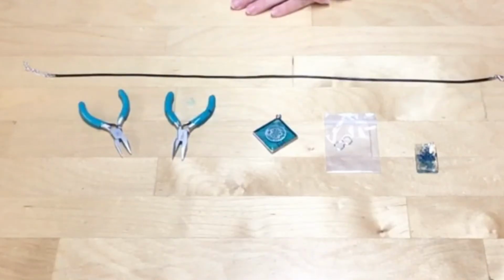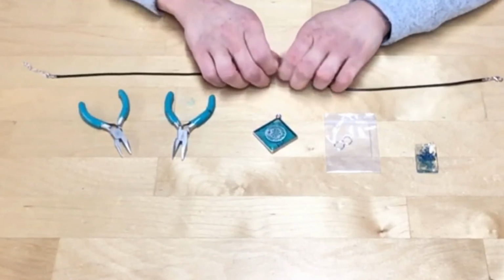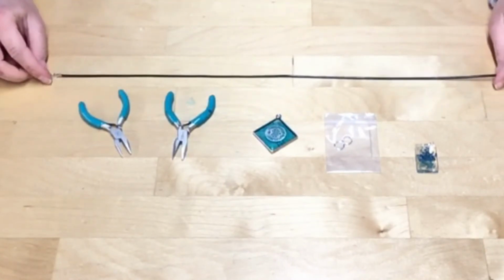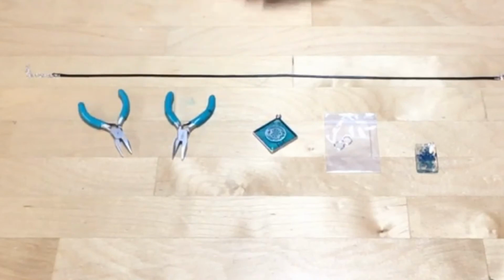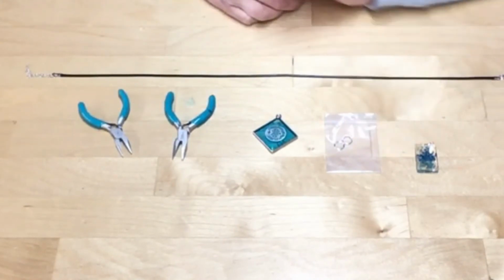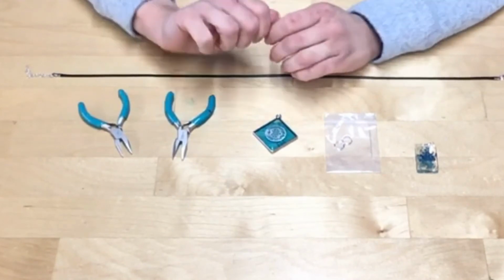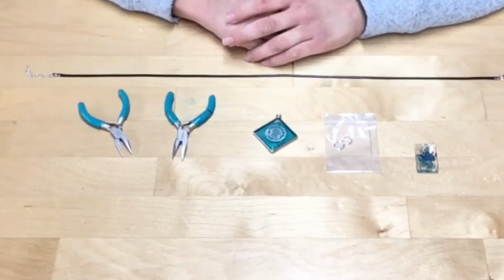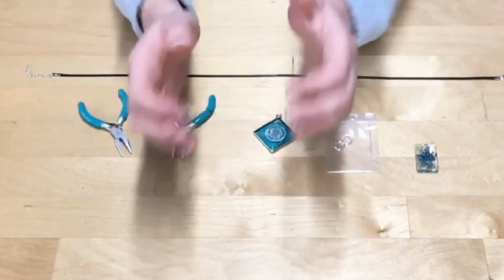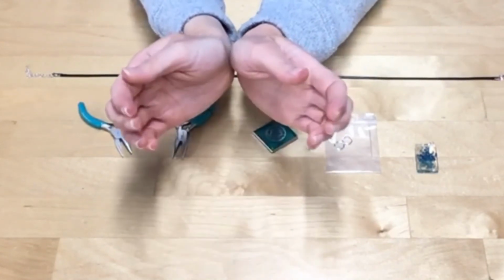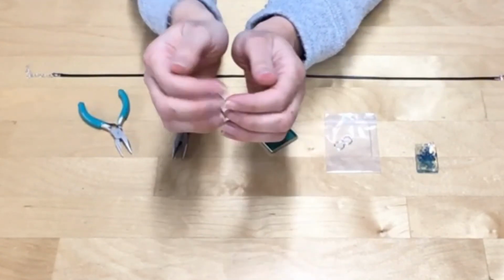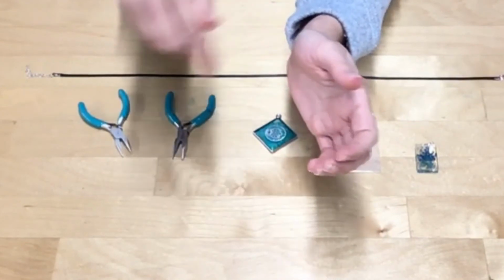Once the resin for your metal frame has cured and cooled off, you're ready to connect it to your necklace cord. For this step, I recommend using pliers if you have some lying around the house. Otherwise, the jump rings we supplied to you are large enough that you should be able to open them with your hands. When you open the jump rings, you never want to open them outwards. This is going to cause the jump ring to misshapen and sometimes even crack.